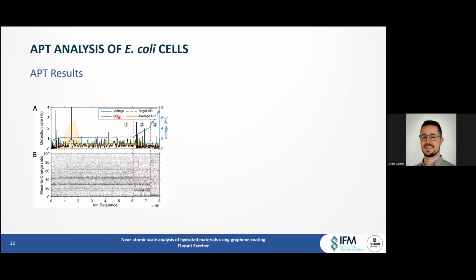And so here, first we have the detection rate right here and the voltage evolution. So there's a clear initial first stage where the detection rate remains stable, close to the set target, and then the voltage increases here in this area. And at the end, it increases even further until we reach the tungsten substrate. So the data set is divided in 3 clear parts, and here we focus on the first one in the green rectangle.